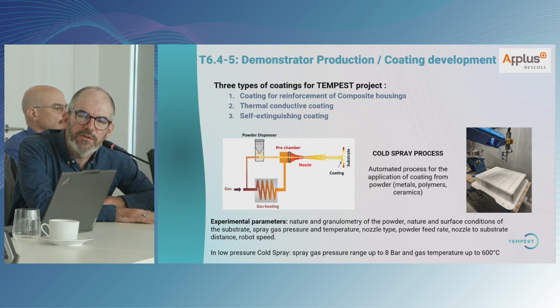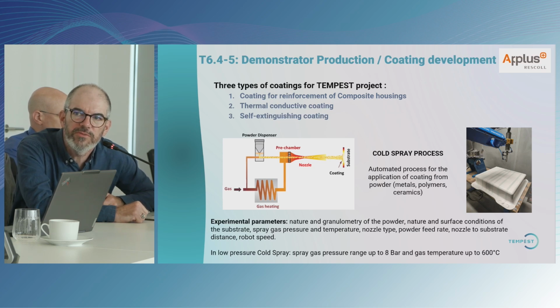Quickly, the principle of cold spray is to make a mix between a hot gas and a powder mix. It can be ceramic plus polymer plus metal, different possibilities. Then you have a chamber, and you inject this mix onto the parts at high velocity, and due to the ductility of the powder mix and also the substrate, you have a nice coating in the end. So it can be automated. You have no solvent, which is indeed a dry process, which is interesting for industry. And we play with the experimental parameters: nature and granulometry of the powder, and process parameters like speed and temperature of the gas.